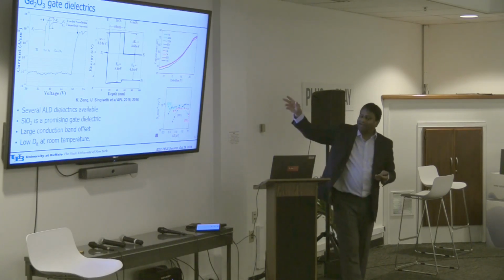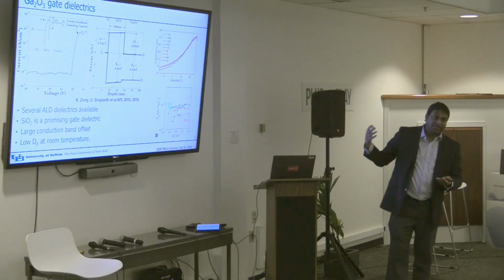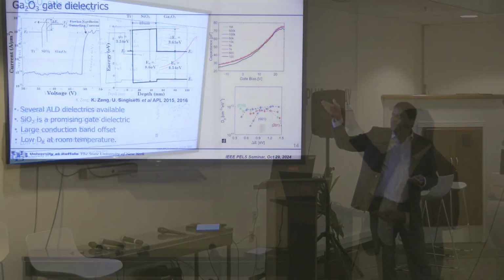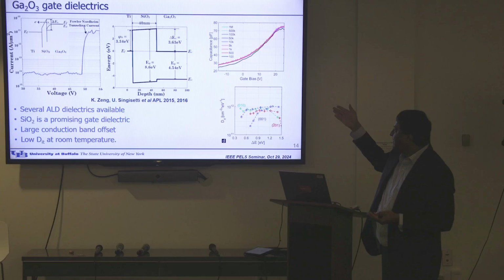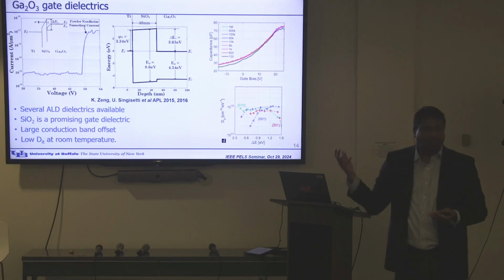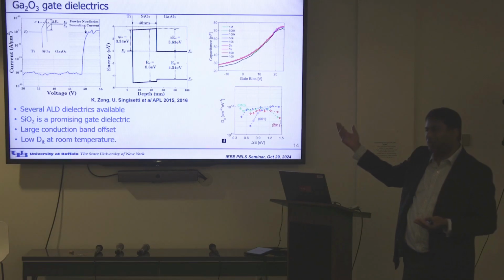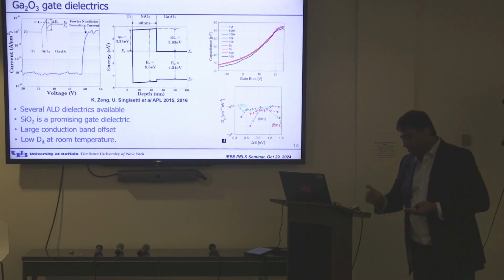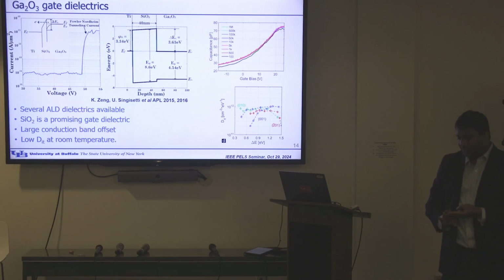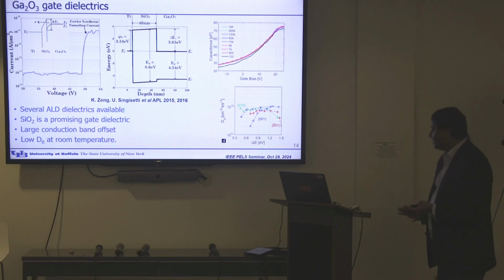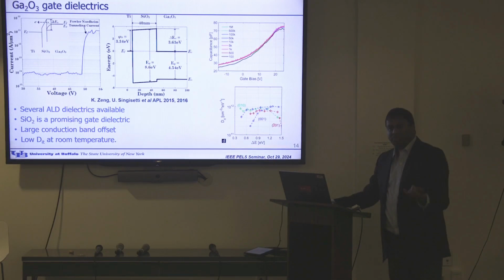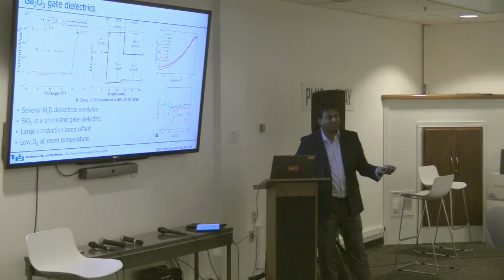This is showing gate dielectrics. If you want to make a MOSFET, you need a good dielectric. This is showing that we have good gate dielectrics, SiO2. You can see in the center here, the band offset is 3.6. Ideally, you want an E-mode device, and this will give you a good E-mode device. There are other dielectrics, aluminum oxide, hafnium oxide, that have been demonstrated. Again, they're also pretty good. Okay, so we have good epitaxial material, good doping control, and good dielectrics. That's all you need. You can make a MOSFET, right?